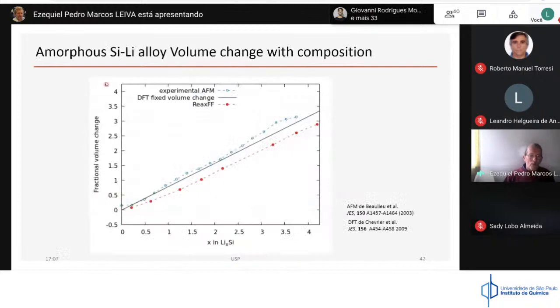One of the things we checked is whether we get the volume change when you lithiate this structure as a function of X, where X is the number of lithium atoms with respect to silicon. These are experimental: the circles and the blue line are experimental results. The black line is the DFT calculation, and the red line is the computer simulation we did with this reactive force potential. That means we are getting at least a relatively good qualitative trend for the increase of the volume of the alloy as a function of the lithiation.